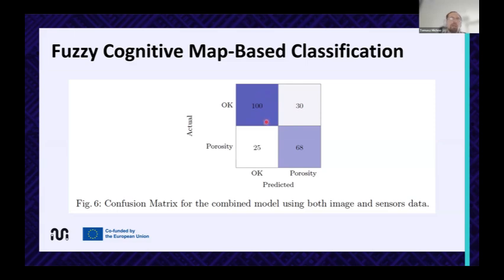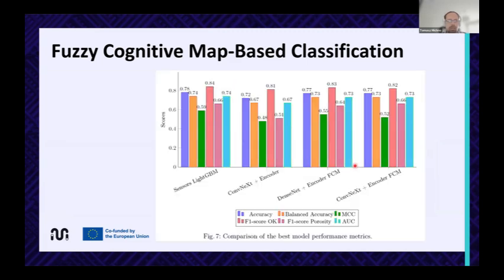So when combining both images and sensor data from these average measurements during the process, we decrease the number of porosity not detected, increase the porosity detected number, and also use okay cases. So fusing data in this use case, the casting, can improve the results. But in this paper, we focused only on the thermal images and only on this small area.